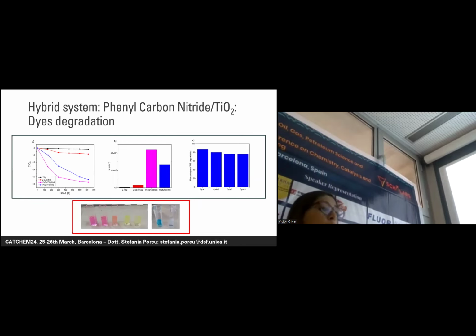We started with the degradation of organic pollutants. So what we did was to study the photocatalytic activity of our hybrid system compared to the deeply studied hybrid system, but with graphitic carbon nitride, okay? So the other pi-conjugated polymer. And we did it using visible light as irradiating source, no UV light was included. So we used a white LED for this application. What we observed was that our hybrid material, both for rhodamine B and methylene blue degradation, which were the dyes chosen for this test, showed a much faster degradation process with respect to the hybrid system prepared with graphitic carbon nitride, and it's because our material is able to absorb the visible light very well.